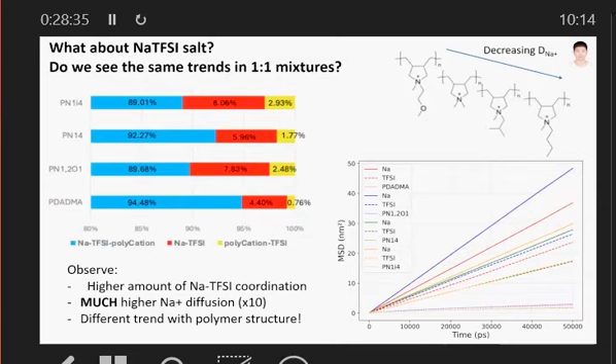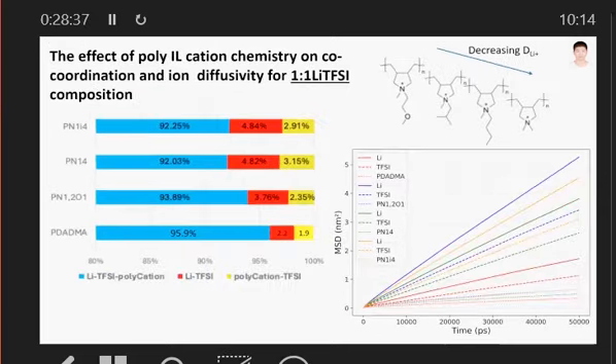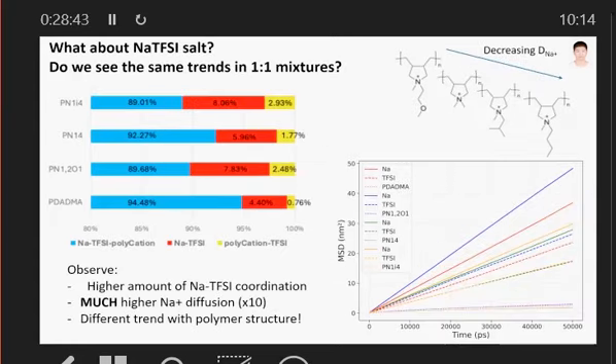But when you look at the diffusivities here, two things to note. First of all, I'll go back one. The number here is 5, right? And the number here is 50. So first of all, as we saw earlier on, the sodium is 10 times more diffusive than the lithium. This is a good thing if you're making an electrolyte for sodium batteries. But also, again, the ether oxygen gives you the highest diffusivity. But now the DADMA is actually giving you a better performance, and putting a more bulky group on that nitrogen actually decreases diffusivity. And this is probably related to the ability for coordination, the ability to change that environment I showed you earlier. The cage environment probably is going to change, because what is allowing that sodium to diffuse, or the lithium to diffuse, is that rearrangement of the coordination environment.